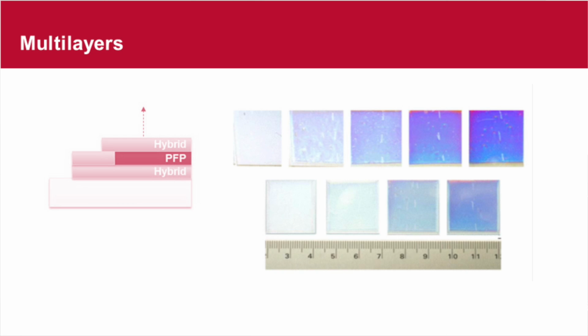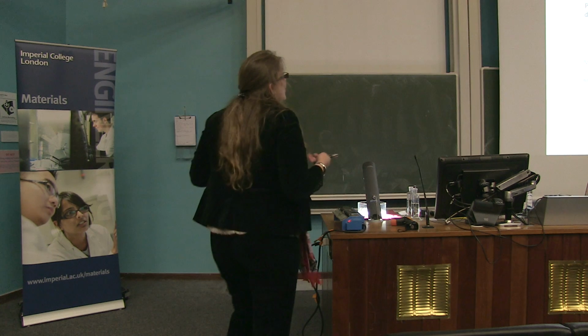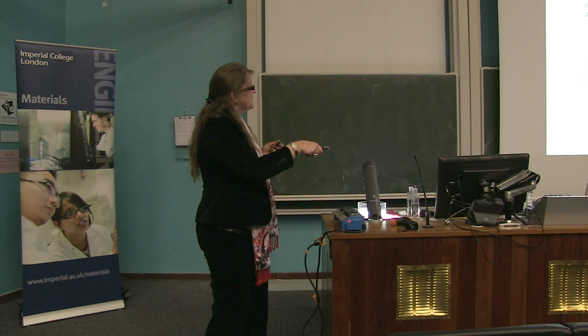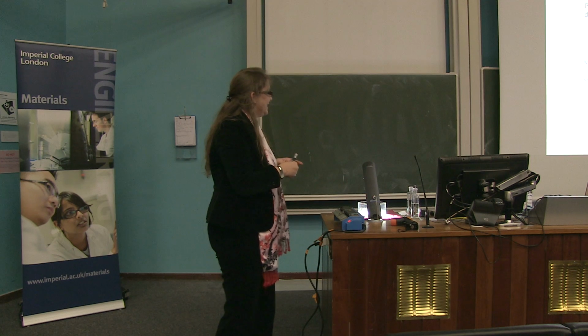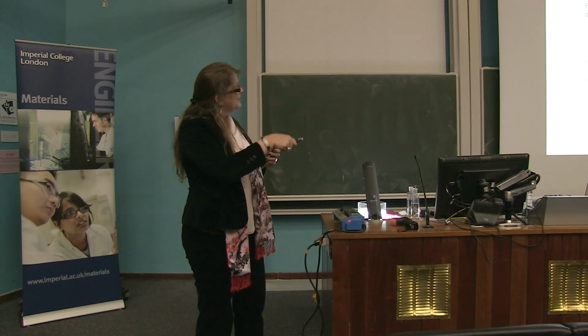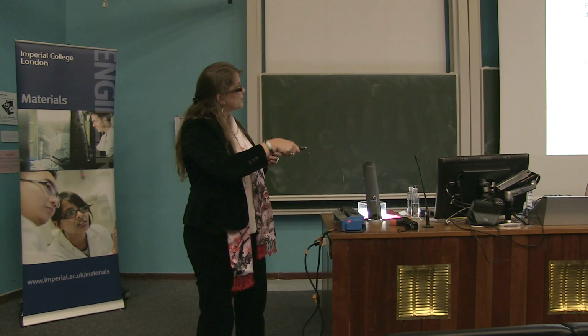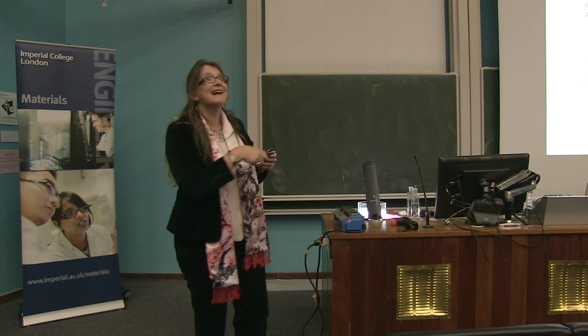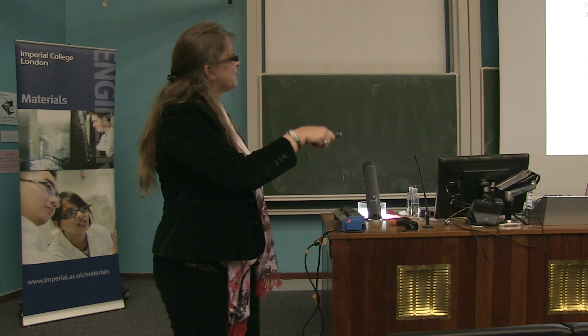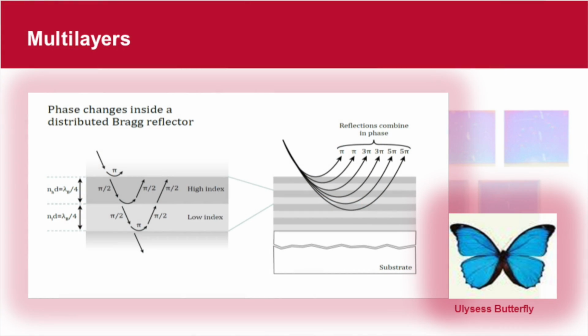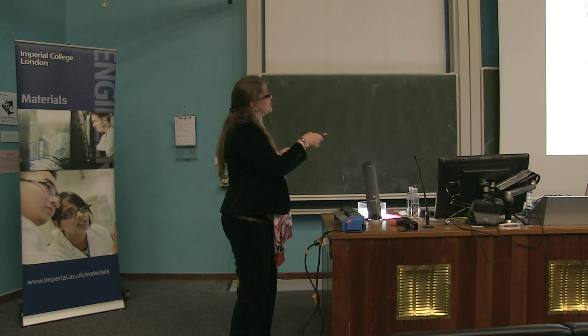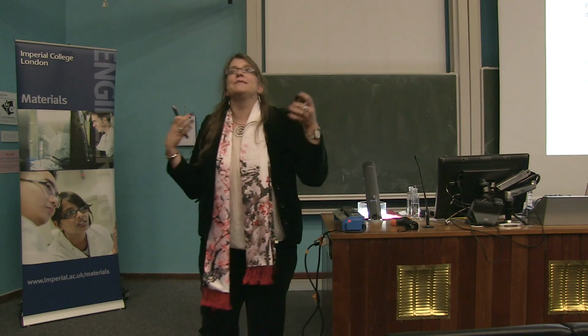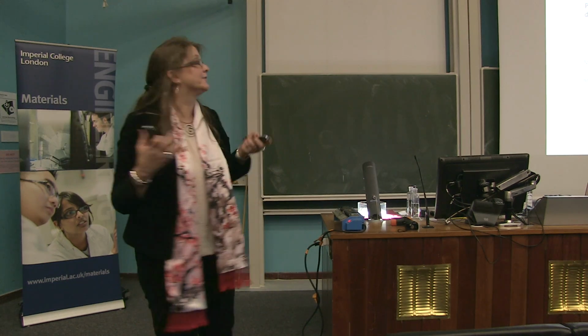And what you see, despite the individual layers are transparent, suddenly the film gets blue. It gets blue because of the refractive index differences, similar like in the experiment I just showed. Sunlight gets actually not transmitted, but at these interfaces between high and low refractive index gets reflected. This is a graph I stole from Envistr's thesis, actually. And these multi-layers we call distributed Bragg reflector. They are actually mirrors, but not made with metals.